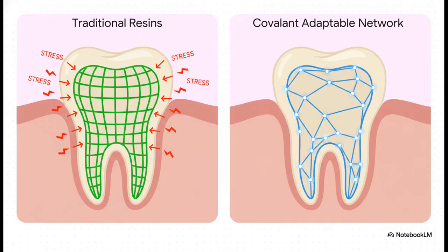So on the left, you've got the old way of doing things. Once those chemical bonds form and lock in, that's it. They're stuck. All that stress from shrinking just gets baked right into the material, permanently. But on the right, we have a covalent adaptable network, or a CAN. The huge difference here is that the network itself is dynamic. It has a built-in way to break and reform its own connections, which lets the whole structure kind of shuffle around and release that stress as it's forming. It's a total game changer.